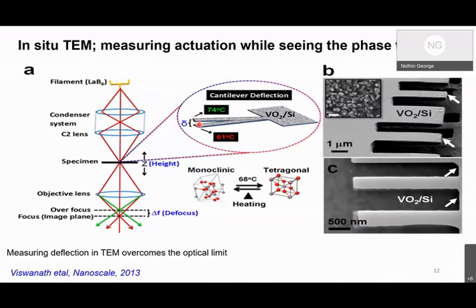Right. We used focused ion beam to make it relatively thick, but we are still able to see the grains and get the diffraction pattern. Otherwise, you are right. It is electron transparent at least to get the basic bright field and also the Fresnel contrast. So the full cantilever is not transparent, only a small portion is. There may be a small gradation in thickness. You are right, the tip is in fact much thinner. I'm showing you the figure, a TEM image at very low magnification. We do have electron transparency to get at least basic bright field imaging. Thanks.